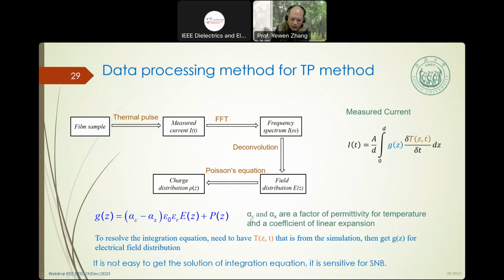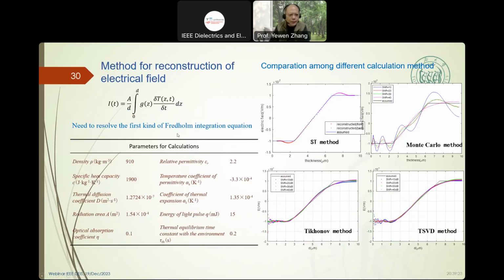This needs to consider alpha epsilon and alpha x, which are factors of the permittivity for temperature and coefficient for linear expansion. So it's not easy to get a solution of the integration, and it's also very sensitive to the signal noise ratio. Oh, this one is a method for the equation. We need some parameters for this equation. We try different calculation methods and we can get different results. Some give results with higher resolution, such as this method. Usually many people use the Tikhonov method, but this one can also be used.